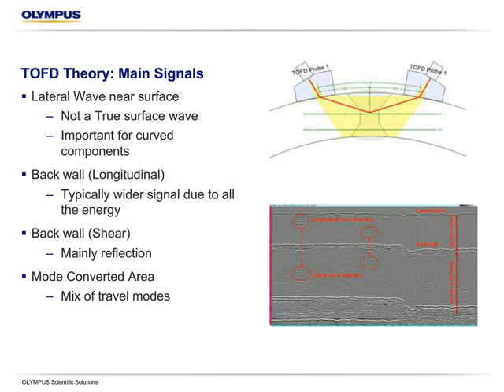Another large one. And then in between that, we have what we call, again, that kind of mix zone or that mode converted area, which may be a healthy mix of stuff that went all the way as shear, part way as longitudinal, part way as shear. Again, good for added resolution of flaws. We might get a better separation between the back wall and the flaw itself, or the lateral wave and the flaw itself, because of the change in travel speeds.